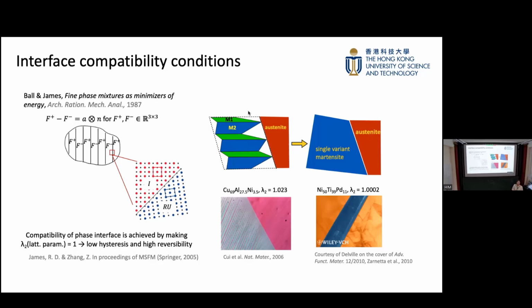And by the Cauchy-Born rule, we find that if we look at the crystal structure, one side is the undeformed austenite, and the other could be some variant of martensite. The point is that the other side is deformed, and as we can see, the periodicity of the lattice truly changes. This becomes a little bit elongated, and this is like a very good square or cubic. In such a way, we still can make the lattice parameters exactly right so that there exists an interface. We solve that equation and we can find such an interface, so that they form this atomically sharp interface.